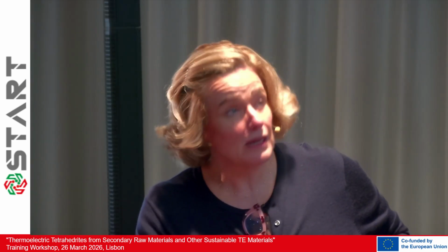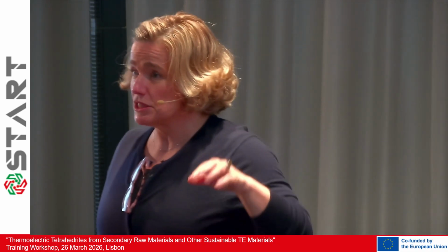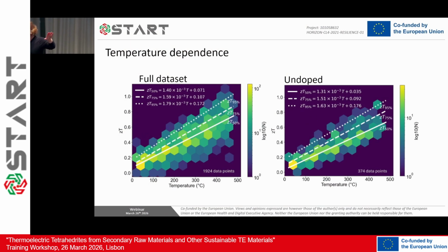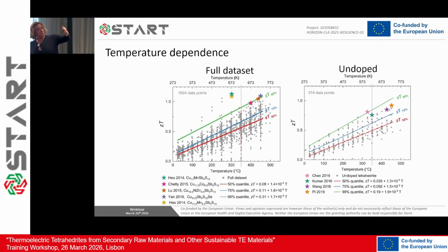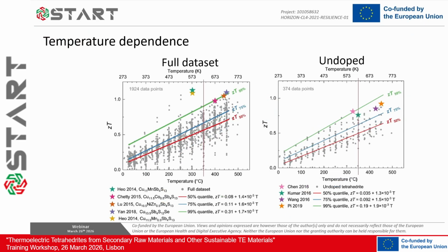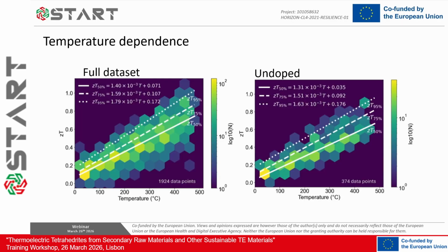But then we found out that the best way to represent this is using these hexabin plots, because with a regular scatter plot you don't understand where the maximum of the dispersion is for each temperature. It's just a cloud of points, and you don't really know if it's more here or there. But with the maps, with the colors, you can see where the center of the dispersion of the distribution is.